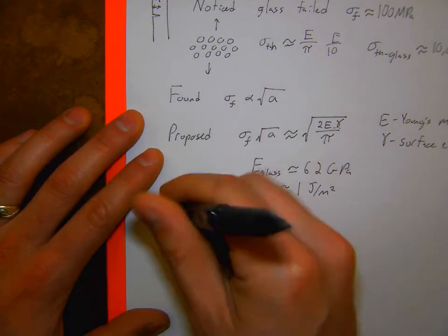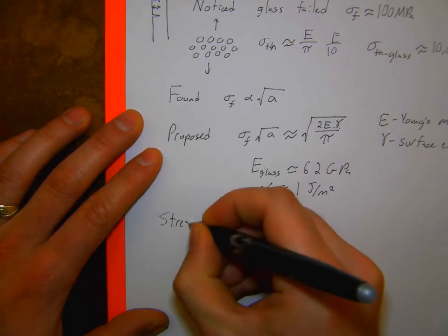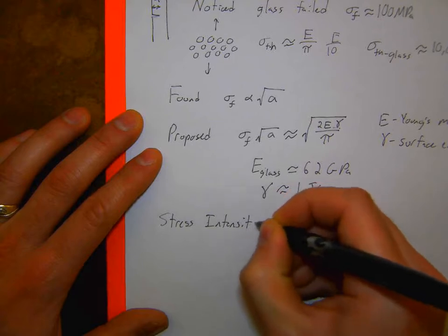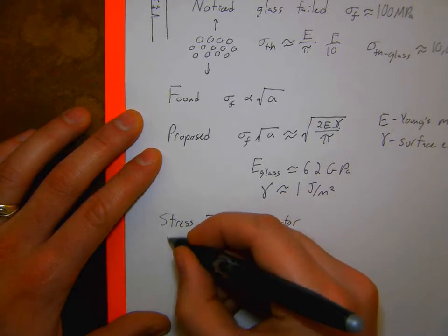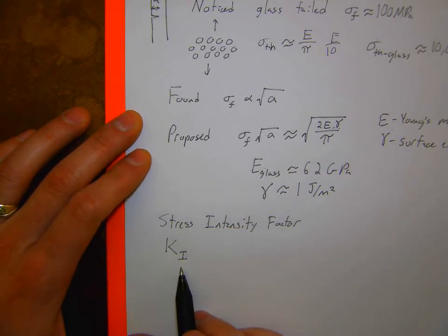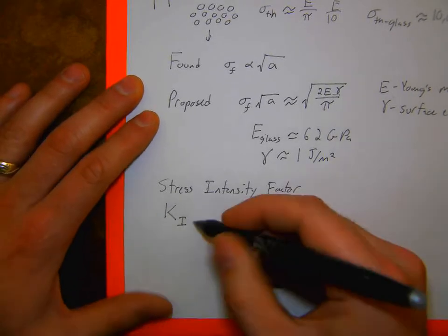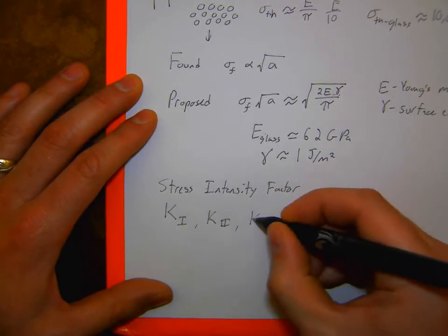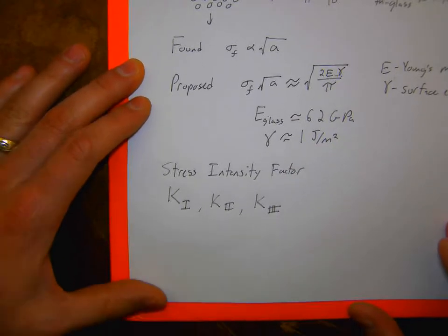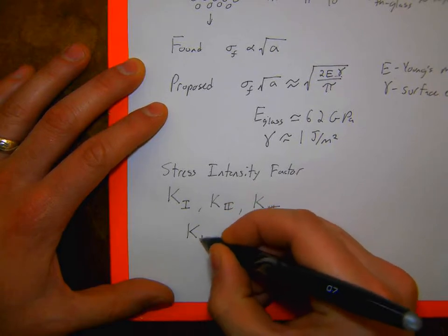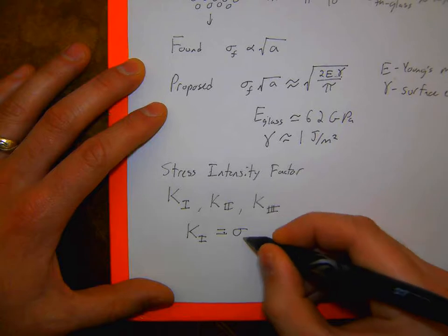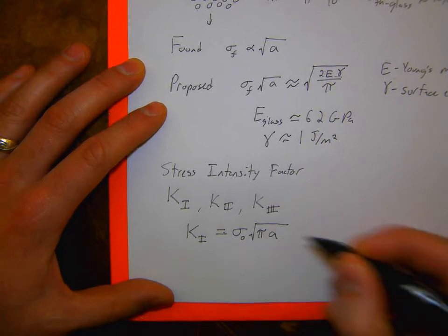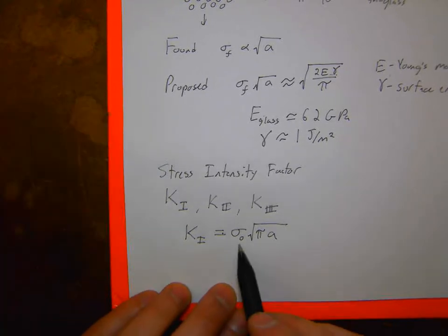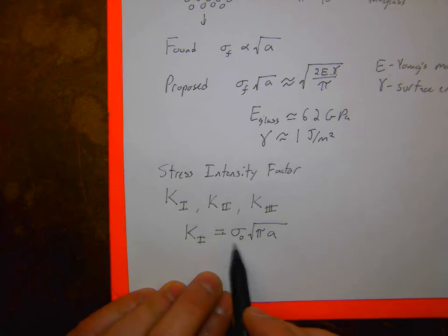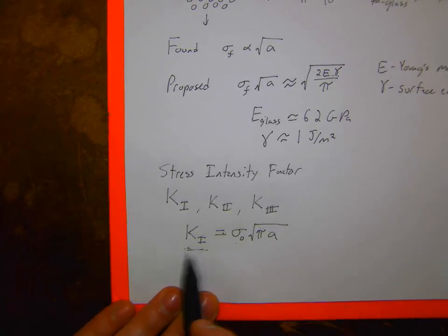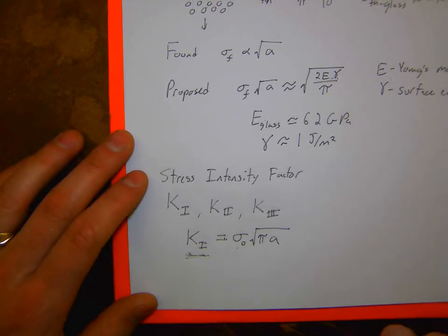We're going to define a stress intensity factor, K. I'm going to call this K, and then I'm going to use some subscript depending on which mode of fracture I'm looking at. So there's a K1, K2, and K3 for all of those different fracture modes. And I'm going to say that this stress intensity, K1, is now equal to the far field applied stress and then the square root of pi a. And so depending now on the length of the crack, the square root of a, and the far field applied stress, there's just some stress intensity in the material. So there's some K1 in the material that's going to cause it to fracture.